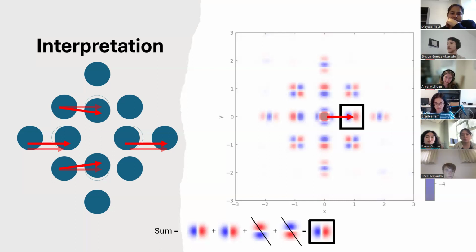Okay. How do you know what atom you're looking at? Sorry, say that one more time. How do you know what atom you're looking at? That's a good question. We know, for one, that with this delta PDF, we're only looking at the changes in the local structure. So when I'm looking at the real space model on the left, I'm only pointing out the atoms that have changed, right? Or the atoms which contribute to pairs that have changed, right? So that's one way of answering your question: right now I'm only thinking about the atoms whose local structure is different than the average structure.